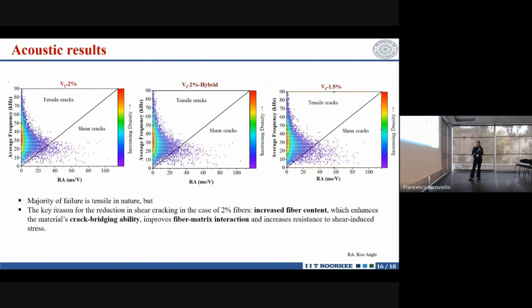And if we see the mode of cracking, mostly the cracking is tensile. To define the mode of cracking, we have the RA value versus average frequency plot. So majorly the cracks are tensile, but as we proceed from 2% to 1.5%, a little bit of shear cracks are increasing. The main reason is that when we have 2% fiber, because of the increased content, the matrix and the fiber have close bonding. It has a greater contact between the two crack surfaces, so it has the ability to bridge it and not lead to shear cracking.